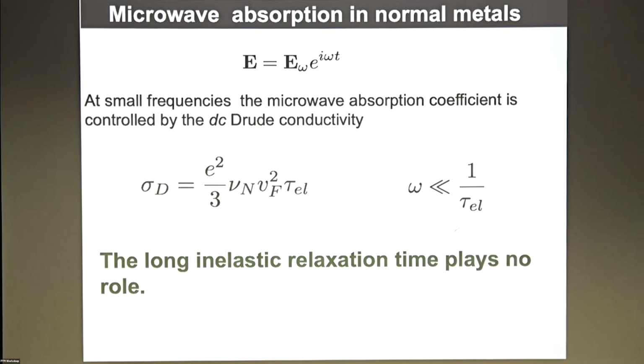So first, microwave absorption in a metal is featureless. It is controlled by the conductivity: the density of states in the normal metal, the Fermi velocity, and the elastic relaxation time, when the frequency is much smaller than the inverse elastic relaxation time. The conductivity controls absorption, and the inelastic relaxation time doesn't play any role. Also, non-linearity in absorption in metals is very small.